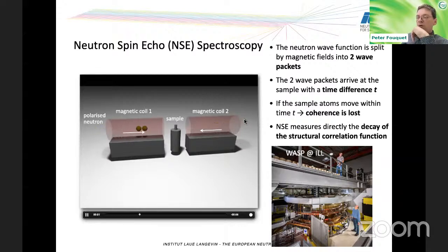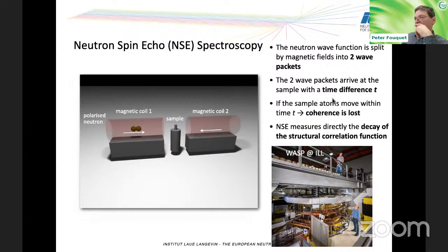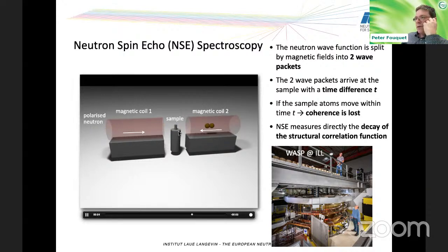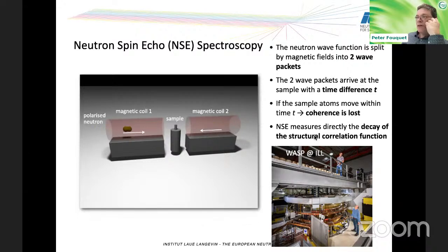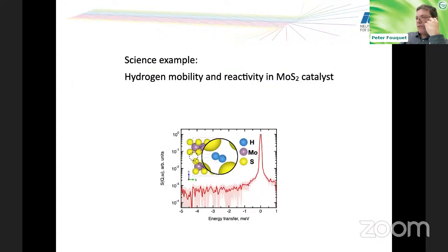And then at the end of this spectrometer, you can measure the loss of polarization of the spin property. And this loss of coherence shows you what the structural correlation function does at the sample with time. So this neutron spin echo spectroscopy measures the decay of the structural correlation function with time. So that's one of the high resolution techniques. And now I want to go to scientific examples.